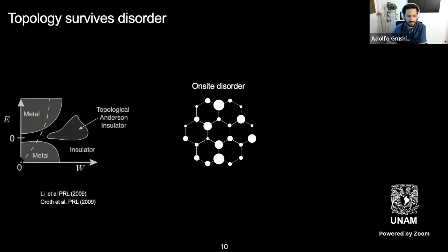The way it works is that, imagine you're plotting the bands as a function of energy, and I park my Fermi energy here. Then as I tune this disorder, which is this W, you suddenly invert the gap. What you have to imagine is that the symmetry eigenvalues change, and the gap is inverted. This means that you enter a phase that is a topological insulator, or a topological Anderson insulator, because it's induced by disorder. Of course, if disorder is very, very strong, then at the end you will still recover an Anderson insulator, meaning that the electrons, if the disorder is infinitely strong, will localize. They will never know that a topological phase ever existed. Nonetheless, this is just to say that disorder not only can be an enemy, it can also be a friend in terms of realizing topological phases.